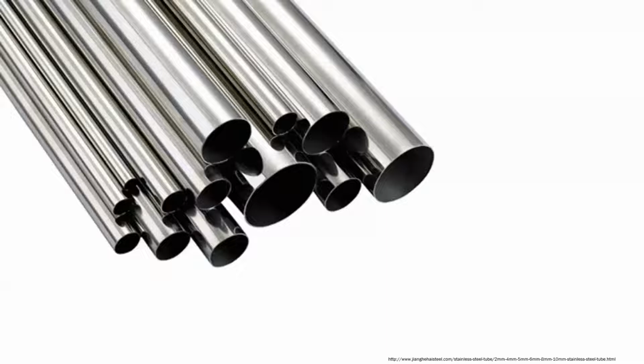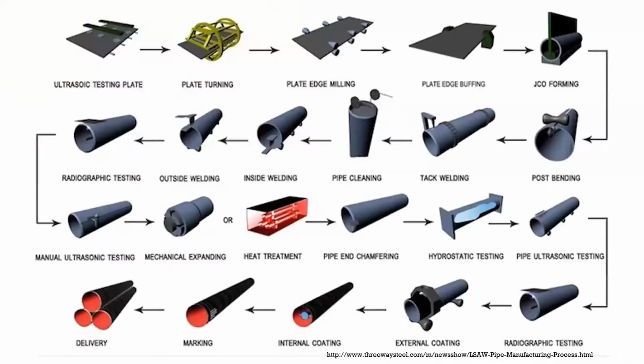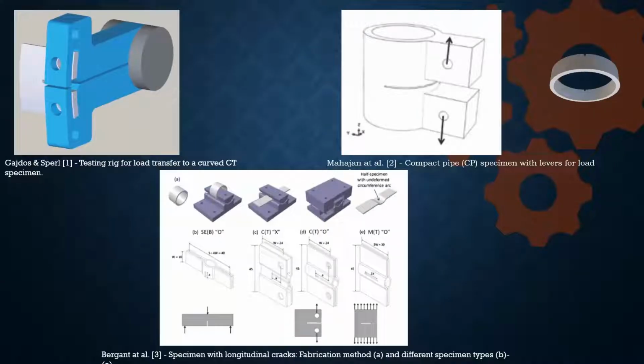The ultimate goal of this study is actually to monitor the fracture mechanics parameters on pipes from which it is not possible to extract test specimens that meet various standards. There are several reasons. First of all, because we have thin-walled pipes which are not suitable for standard tests. Even if we take the sheet metal from which the pipes are made, we would not get a realistic picture, because during production there are many steps such as bending, welding, heating, cooling, etc. All these processes essentially change the mechanical characteristics of the material.